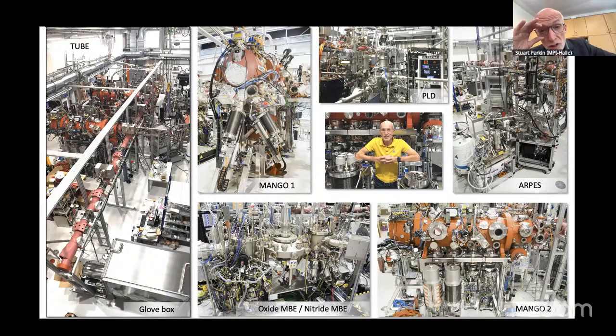We can have 44 different sources, so we can make structures from a wide variety of different materials, and each of the layers that we form can be atomically thin. In this way, we can make complex structures. We can also combine this Mango system with a pulsed laser deposition system using energetic beams of light, or with a molecular beam epitaxy system. We have two systems connected to this tube. One is designed for oxides, one for nitrides, and we can automatically switch a substrate between one of these systems to combine complex heterostructures formed from these very different thin film techniques in this way.